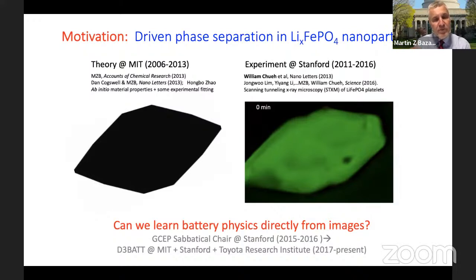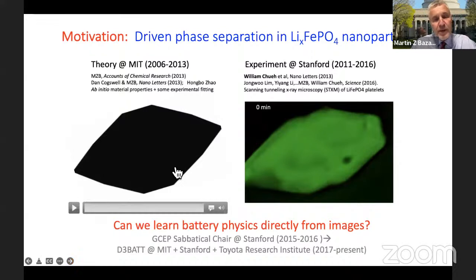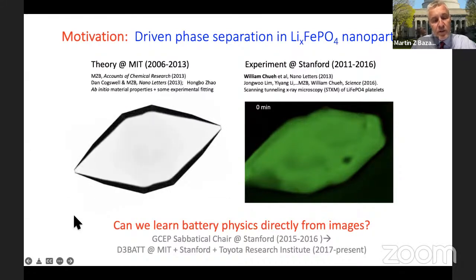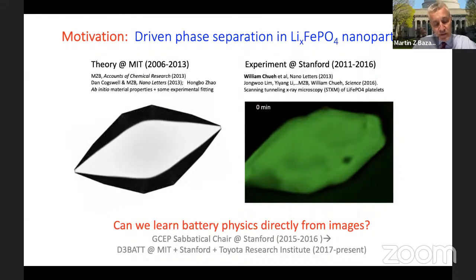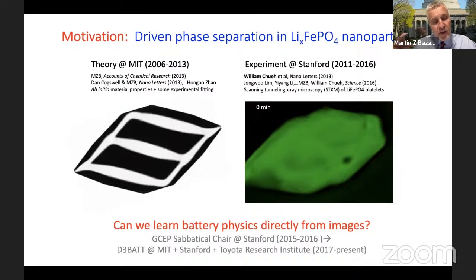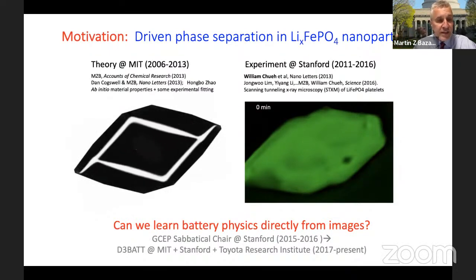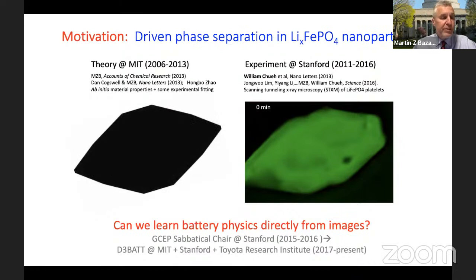And what's special about this material is that it's phase separating. So rather than having individual lithium ions go into this material and diffusing freely throughout the system, they form stable phases, which then evolve and grow, nucleate, and form these interesting patterns. So already by 2013, we could do this kind of simulation entirely using combinations of experimental data and, in particular, quite a bit of ab initio quantum mechanically calculated material properties, so predictive material properties.